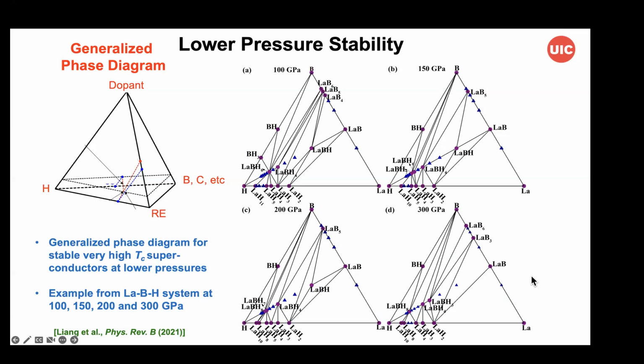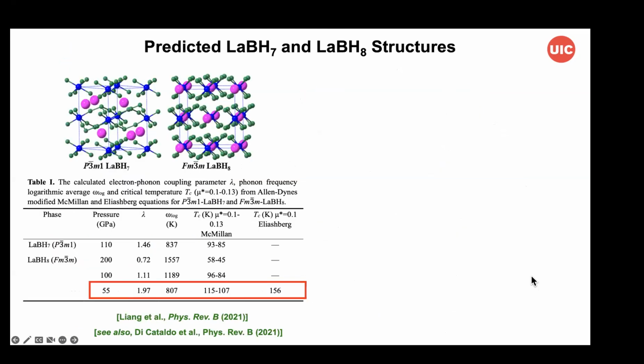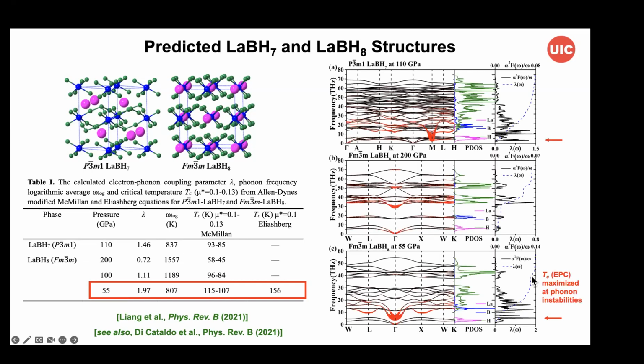And this particular system, the LaBH8 system, is interesting because one finds that LaBH8 has fairly low pressure stability, a dynamical instability of around 50 GPa, while still retaining fairly high Tc. This is work that was found also by the Italian group. And you can again see that what's limiting this, but also maintaining the very high Tc, is these dynamical instabilities that one reaches on decompression in the system. So it's very strong electron-phonon coupling that gives rise to the maximal Tc.